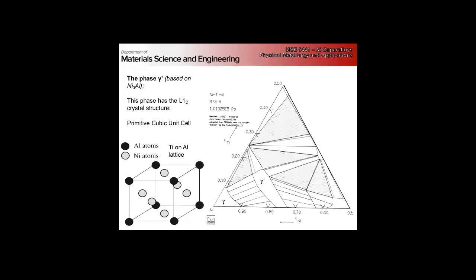If we have a 1/2 110 dislocation, what's it going to do? It's going to translate aluminum onto a nickel site and nickel onto an aluminum site. So we need 2 dislocations to come through to put us back to our regular configuration. So a regular FCC dislocation, 1/2 110, becomes a superpartial in the gamma prime and causes an APB.